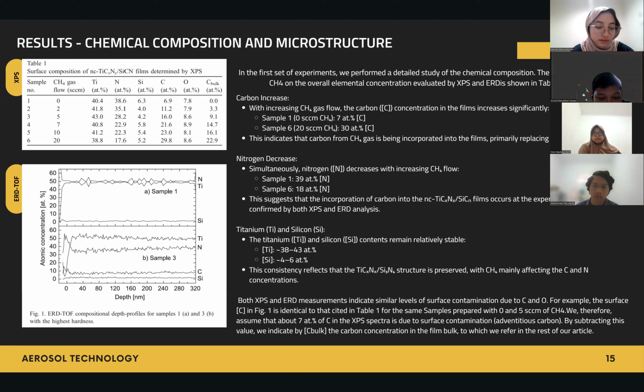Here we can see from table 1 that with increasing CH4 across the 6 samples, the C, or carbon, is increasing, replacing the N at the end, which is the nitrogen. So if the carbon is increased, it will replace the nitrogen, and the nitrogen will be decreasing. We can see from sample 1 and sample 6 that the carbon is increasing from 0% concentration in the bulk to 22.9%, while the nitrogen goes from 38.6% to 18%. This measurement also indicates similar levels of surface contamination due to C and O.